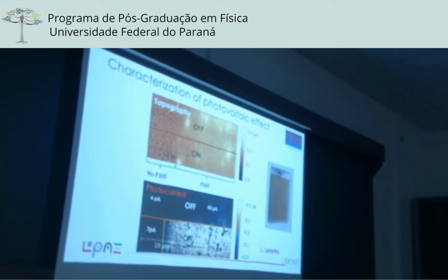This measurement could cause accelerated degradation of this material. We can control that. No, you're right, because you apply voltage and of course you can destroy the layer. But the idea here was to show that we can generate photocurrent out of the system. For instance, for the perovskite, we worked a lot on the stability of the perovskite by controlling the atmosphere around the perovskite.